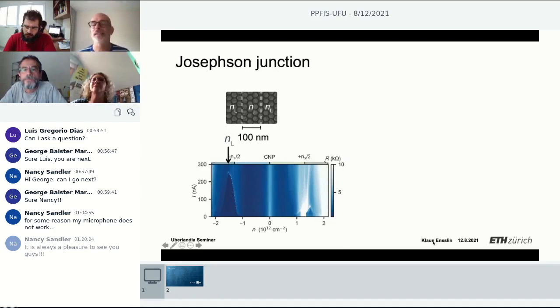We have done that for gallium arsenide for many years. Now we are doing the same thing for graphene. It's an obvious thing. It has to be done. Let me just give you one example why it's much harder. What you do is you have a quantum dot, and then you come with a gate, and this gate is coupled to the resonator. Now, our graphene quantum dot sits on a piece of graphite, which is a fantastic conductor. So now you come in with your electrode from the side, and part of this line that goes to the dot has graphite below. So it's a huge capacitive short. What that means is that the signal that we see from the dot is covered by the signal that we see from the graphite backgate.